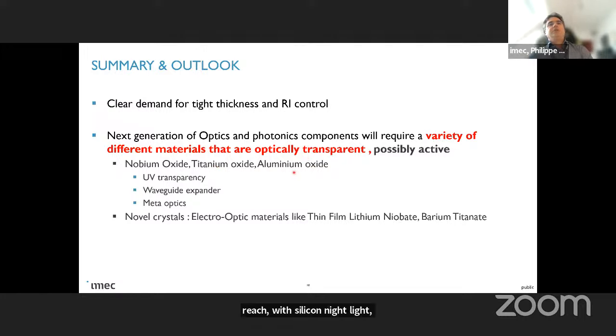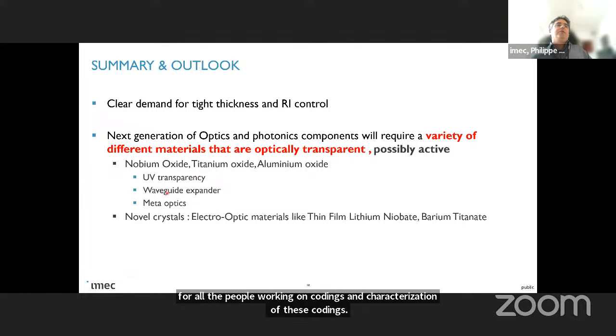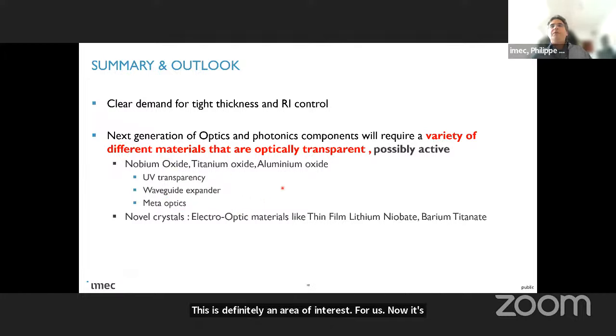We are also seeing regions of the spectrum that become more and more interesting. So aluminum oxide for UV transparency is very important. And we see these three kinds of materials really coming up. So for all the people that are working on coatings and characterization of these coatings, this is definitely an area of interest for us. Now it's maybe a bit out of scope, I don't know, but I just want to mention that. As I mentioned, only silicon is active. So when you apply a bias to it, it can do things that the other materials usually cannot. So we are looking at new kinds of electro-optic materials like thin film lithium niobate and barium titanate.